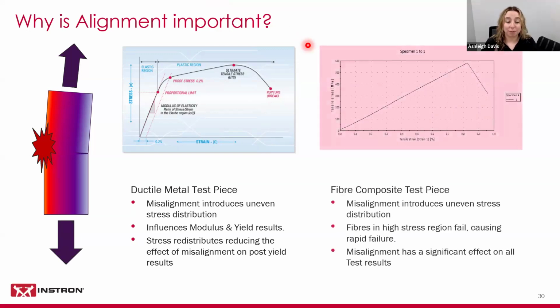If we compare that to a composite specimen, if we're misaligned, composites are particularly sensitive because they generally are brittle and have low strain. For example, you might have a thermoset resin-based composite in aerospace. Your fibers are going to be very brittle. And if you've loaded it and it already has a pre-stress and those fibers have begun to break before the test even starts, we've essentially lost the strength of the specimen. When you have those first fiber breaks, you're going to essentially have a successive rapid failure of the whole specimen. It can't handle carrying that load and redistributing that load like the metal specimen can.